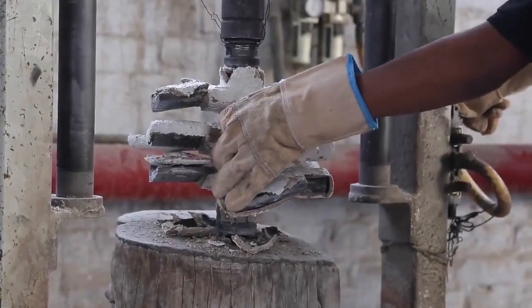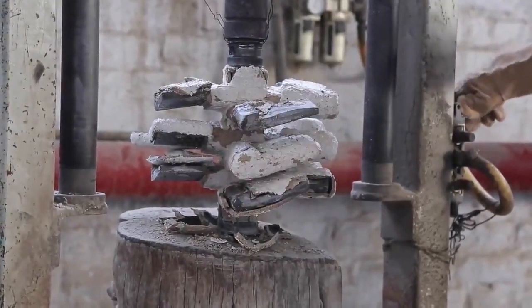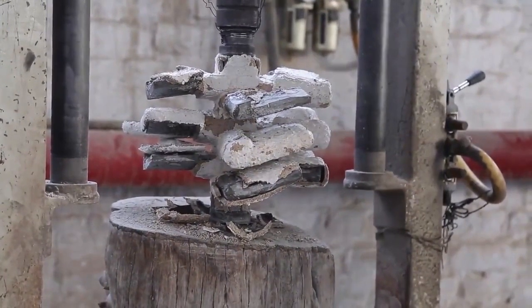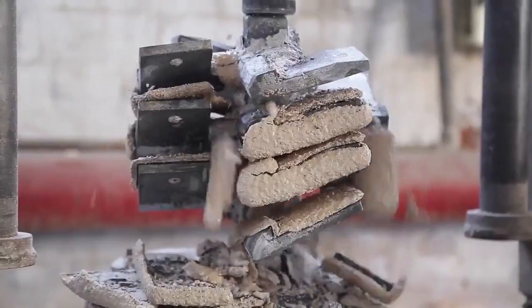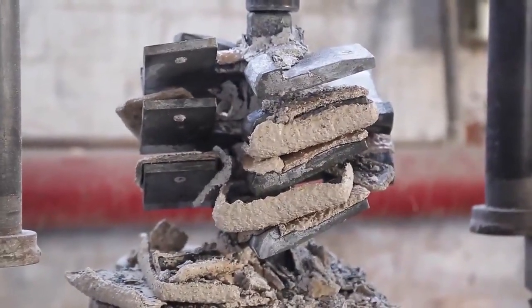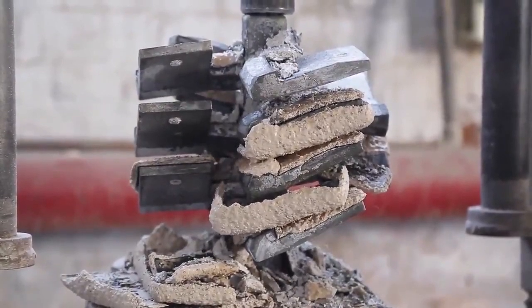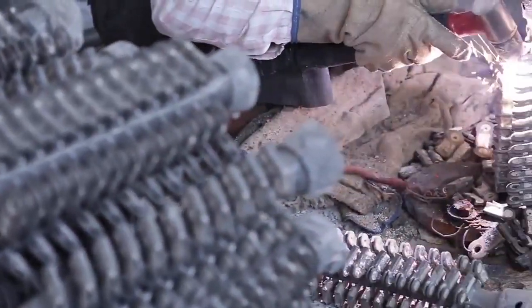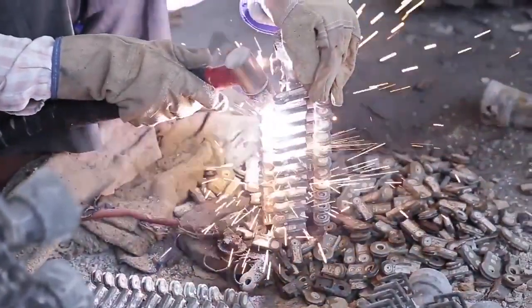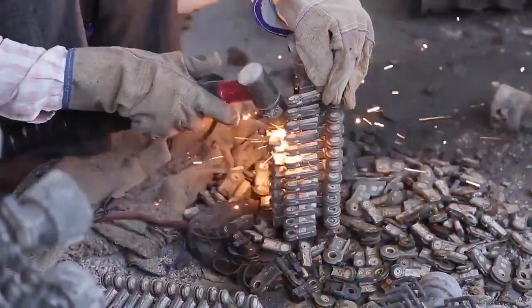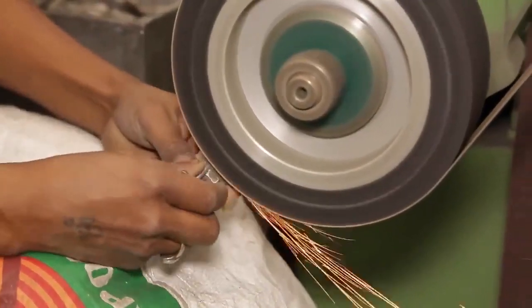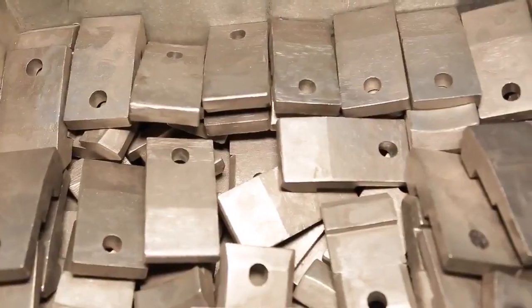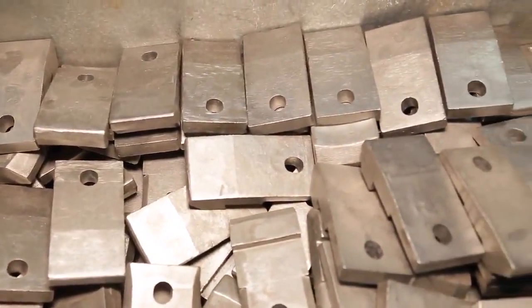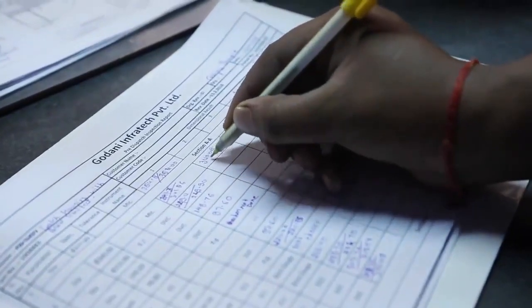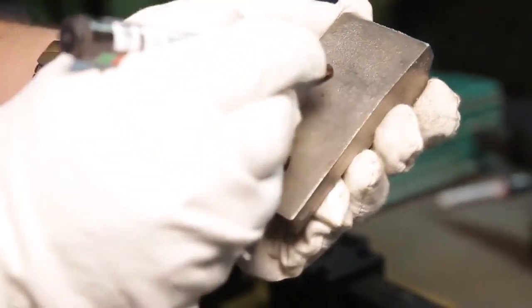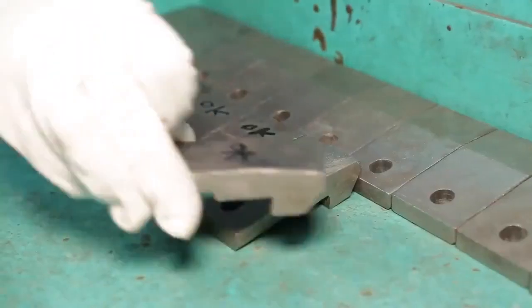Because of metal shrinkage due to solidification, much of the ceramic shell literally falls off the castings. However, additional cleaning is required to remove all the shell material. This is normally accomplished mechanically and/or chemically. Following initial shell removal, the individual castings are removed from the gating system by some means of metal cutting. Any additional cleaning and processing steps are then done to finish a complete investment casting meeting all the customer expectations. Finally, the castings are checked for adherence to drawings and quality standards, post which the castings are sent for packaging and shipping.